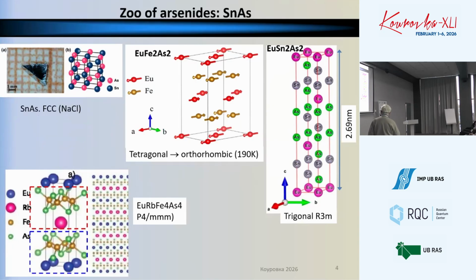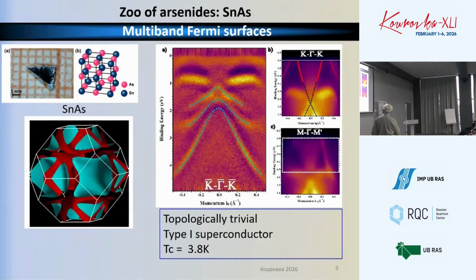Here are more complex materials which superconduct, and I will be talking about pure compounds with no dopants. So it makes the physical picture clear and helps to understand what is going on without any effect of impurities. Now, just to start with a very simple tin arsenide. This is an FCC cubic structure of sodium chloride, and it is a regular semi-metal. You can see here holes and electrons, and based on the experimental quantum oscillation measurements, these are particularly our measurements, you can reconstruct the Fermi surface.